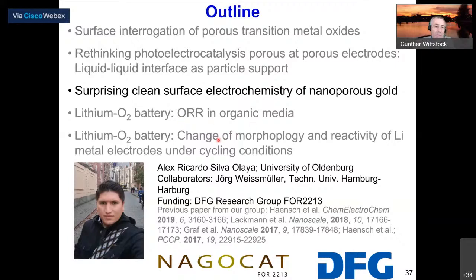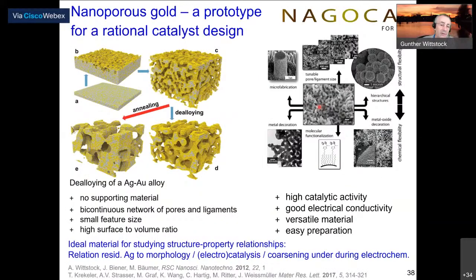I think I would like to bring you one more example, and that is the surprisingly clean surface electrochemistry of nanoporous gold, which we also investigated with these cavity microelectrodes. So nanoporous gold is a material which is obtained by dealloying a silver-rich gold-silver alloy. Silver and gold form solid solutions, so they are miscible in any ratio. And we get a network of ligaments which does not need any supporting material. It's bicontinuous, so there's a continuous metal phase and a continuous solution phase with small feature size and a high surface to volume ratio. It can be surface modified, has catalytic activity, and is a rather versatile material, which we use to study structure-property relationships systematically.